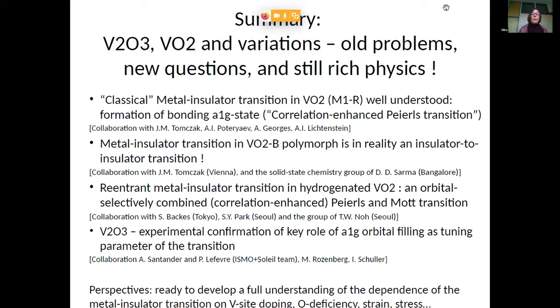And then I have shown you the new surprise in the VO2 B phase, where people believed that it was a metal insulator transition, but where we advocate that one should rather think of it like an insulator-to-insulator transition with this little twist that the overall electronic structure is very, very strongly temperature dependent. I have shown you the hydrogenated VO2, where you have the all-in-one inclusive correlation-enhanced Peierls transition in one orbital and a Mott transition in the other. And finally, the V2O3, the movie. Thank you very much.